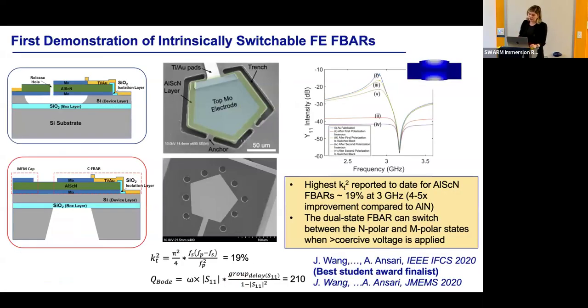Now we went on and built FBARs, or film bulk acoustic resonators, which are these thickness extensional resonators that I showed before, using these ferroelectric materials. So here you can see the SEM images of 2 types of FBARs, one that is released by releasing the silicon device layer on an SOI substrate, and the other one which is released from the backside by using the bulk of the silicon.